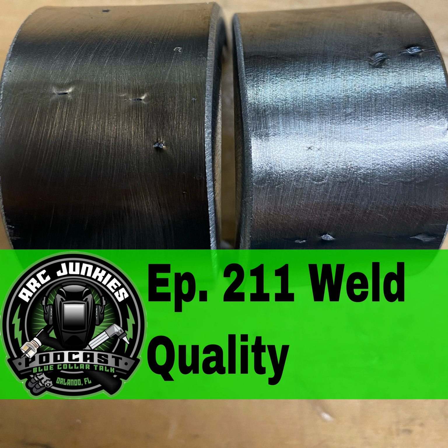Now, on the same side of that coin almost is incomplete joint penetration. We typically see incomplete joint penetration on open root welds, or sometimes welds with backing, where it occurs when the filler metal fails to penetrate and fuse with the area of the weld joint. So if we cut apart a groove weld, whether it's open root or with backing, you're going to be able to see that lack of penetration in there. The weld metal didn't quite reach the back side of that plate, which anytime we're doing open root welding, that's our goal.